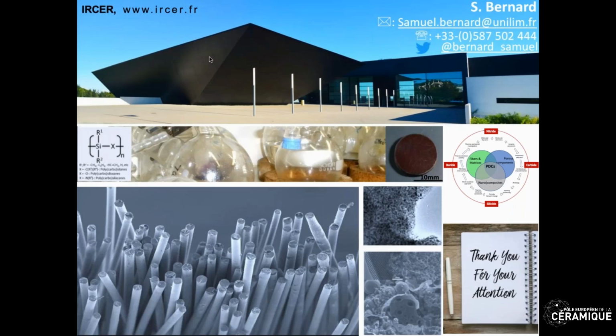Yeah, as I mentioned, the big problem is that you should use chemistry to prepare your polymer, but in fact, you can ask a startup or companies that produce ceramic polymers. But the main issue, I would say, is the use of oxygen-free atmospheres. So to transform your polymer into non-oxide ceramic, of course, you need to use argon in the case of carbide, ammonia in the case of nitride. And to manipulate your ceramic polymers, you need to use a glove box. So I think it increases the cost of your materials, but at the end, this is a balance between the properties of your materials and the cost.